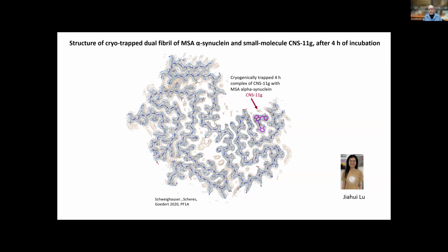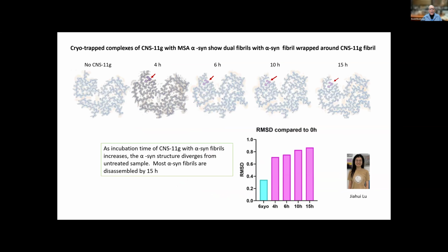So they're metastable. So then she pursued this by determining the structures of cryotrapped material at 4, 6, 10, and 15 hours. And in each one, there's the structure of the small molecule, which is faded out here, but it's here. You can see it in each of these. I hope you can see it. CNS11G in each of these. If she waits longer than 15 hours, well, then there are no fibers.